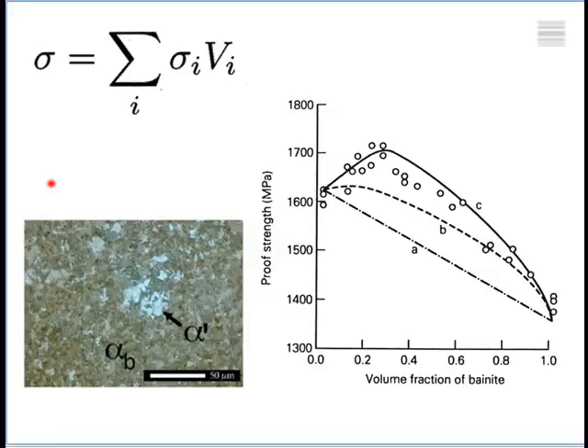Okay? Now, of course, you can see that this is not correct because the experimental data are far away from this line. As a first approximation, it's okay, because bainite is weaker than martensite, so the strength should decrease. However, there are complications, because as we form bainite, the composition of the martensite changes, which is why we get a peak in this curve instead of just a linear variation with the volume fraction.